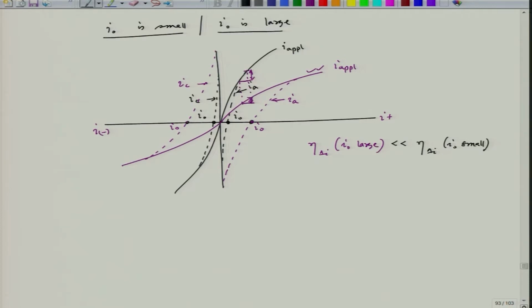So, now that means if I0 is very large for that reversible process, let us say I consider the hydrogen evolution reaction, H+ + 2e- equal to H2. For this process, in one case I0 is very large, in another case I0 is very small, and this side is indicating H2 minus 2e- equal to 2H+, and this side is 2H+ + 2e- equal to H2. So, this is the cathodic, this is the anodic process. Now, it means that if we try to design a hydrogen standard potential cell or a reference cell with a metal having very large I0, even if there is a small amount of current perturbation because of the process that is going on.